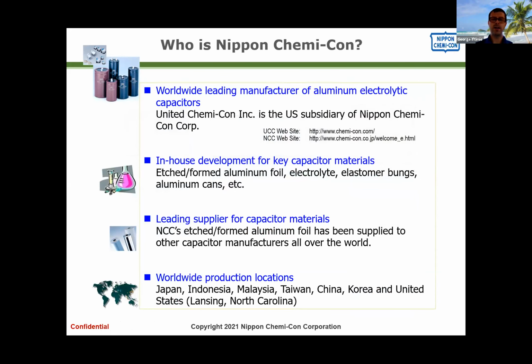As Aparna mentioned, we are the leader of aluminum electrolytic capacitors. That includes the polymers and the hybrid that I mentioned earlier. We have roughly 30% or so of the market share, depending on which time of the year you look at. We tend to be vertically integrated, and the biggest reason for that is quality control. We found that it's much more difficult to control quality, especially for the key materials like foil, electrolyte, rubber bungs, and so on, if we go to a third party which supplies to multiple customers.